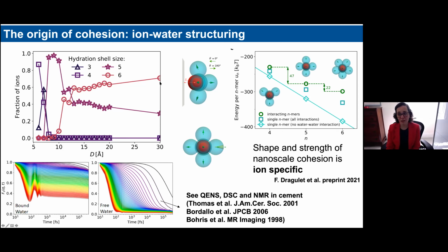The stability of this structure changes with the degree of confinement. As you increase the confinement, the stability of this structure becomes higher and higher. As you decrease the space available, what you get rid of is the water that is bulk-like because it is free. All the water that remains is water that is very persistently bound to the ions. And as you increase the degree of confinement further, you select a different type of structure, depending on how much water is available and which structure you can pack into the more and more confined space.